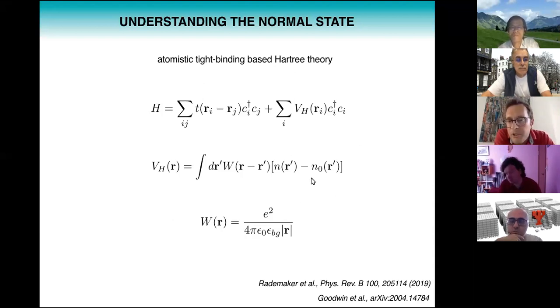Let me also say that we need this reference density basically because we can only do periodic calculations on a neutral system. So somehow, if we want to study doped systems, we have to put in some balancing charges. And in addition, we also want to avoid a double counting of interaction, because the hopping parameters here are fitted to DFT, and the DFT already contains some Hartree interactions within itself. So we don't want to double count, and that we can achieve by subtracting an appropriate reference density.